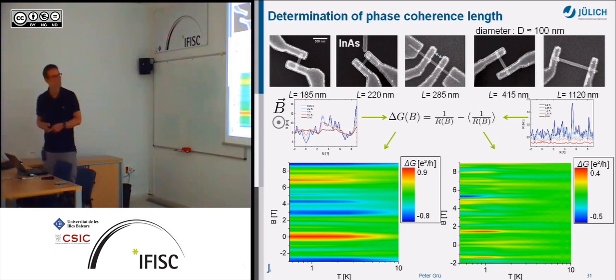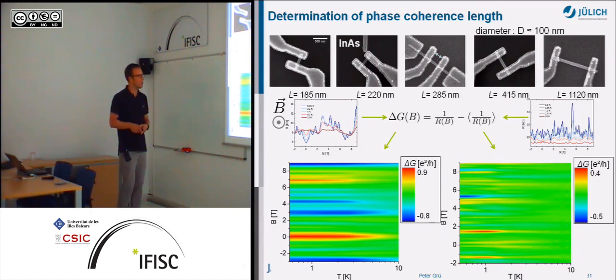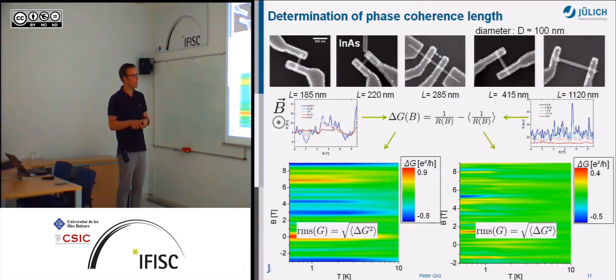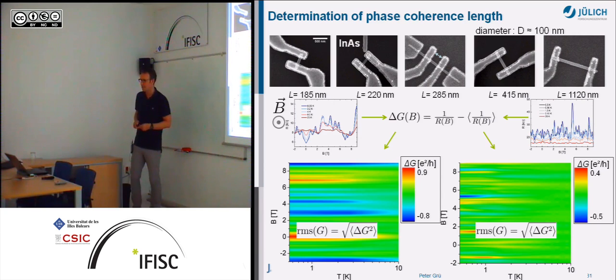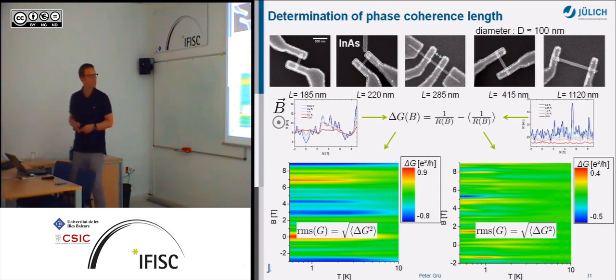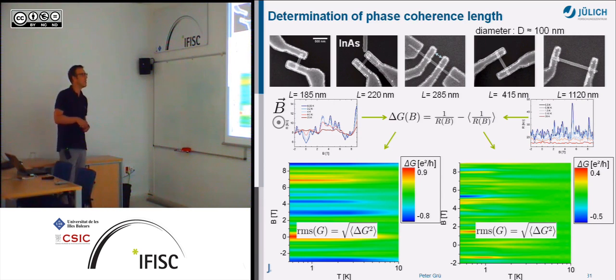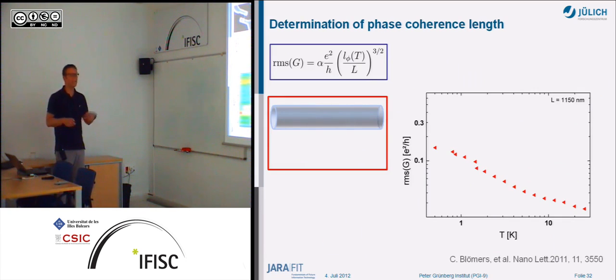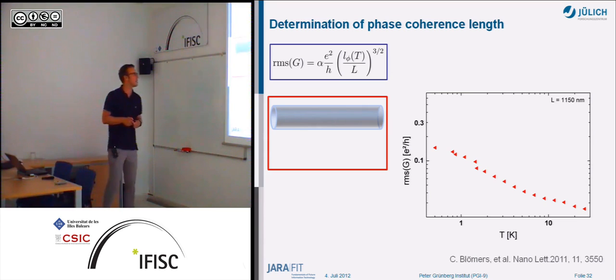You can plot this in a two-dimensional scheme here. So here is the temperature, this is the magnetic field, the color is the amplitude. You see that for the short nanowire, the fluctuations remain to much larger temperatures, while for longer nanowires it is cut off very quickly. That's what we look at. We study now how the fluctuations change if we change the length of the wire, and can we get some information about the phase coherence length here.